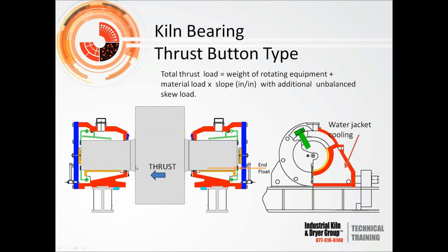And another method that we use to see how much thrust is being applied to, say, the downhill bearing or the left bearing for this example, we can actually put a micrometer measurement on that and actually see the bearing rotate slightly under load. Right. So, there's different means to determine what the thrust load is before you have a hot bearing. But it goes right back to the fact that when you're training a kiln or a dryer, you've got to get the distribution on all the rollers so you don't have one bearing doing all the work. Due to the design, essentially, if you get a decent balance, you're not going to have a hot bearing.